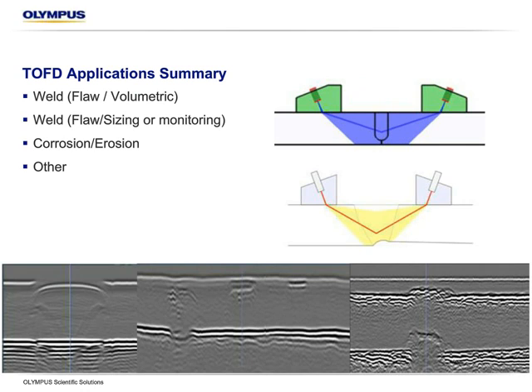So, application summary. There are a lot of applications of TOF, but by far the two biggest ones are one for weld and flaw detection, and one for corrosion and erosion. So when we look at weld inspections, we're usually doing one of two things. I'd say about 80% or better is for volumetric flaws within the weld, and then a little bit on sizing and monitoring, as a kind of complementary technique. If we know a flaw is there, we want to watch it to see if it grows before we have to make the call to shut that down when it becomes a critical length or height. And the other one being corrosion. So on the display, you can see the differences here as well.